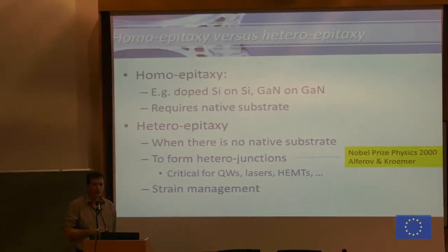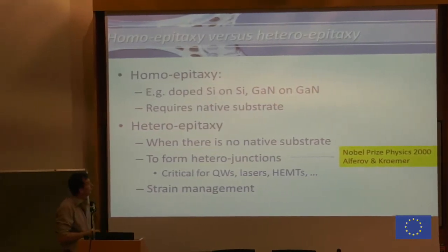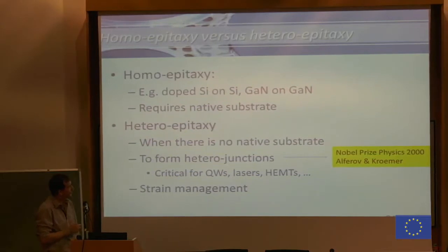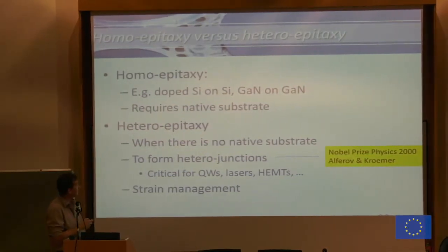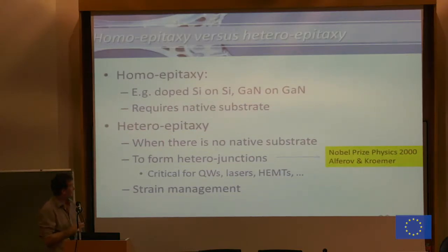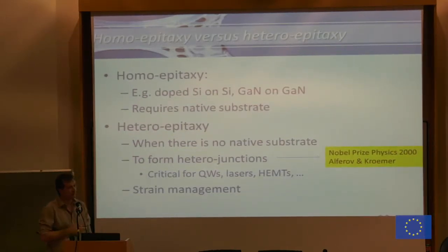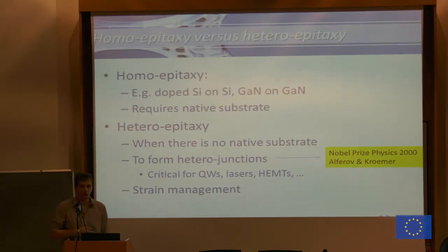I want to move now in the direction of gallium nitride on silicon growth. For that, you should know there's a difference between homo-epitaxy, where you basically grow the same material on top of itself. It requires, of course, that you have native substrates, so that substrates of the starting material are available, which, for instance, for gallium nitride is an issue, but I'm sure Elke will discuss that in detail. Now, what we do in general is hetero-epitaxy, so we start with a certain substrate material and we grow all kinds of different materials on top of that. The nice thing is that you can form heterojunctions with that.